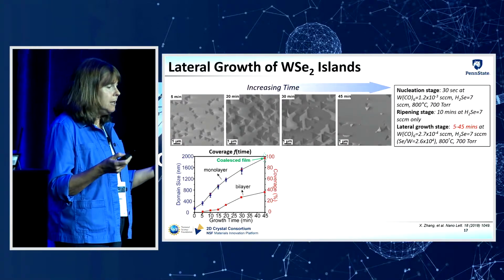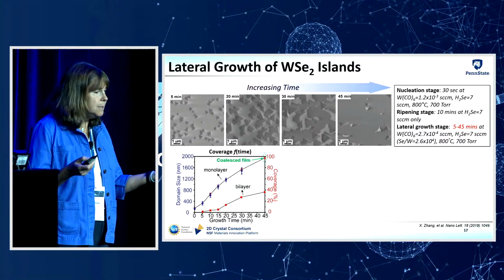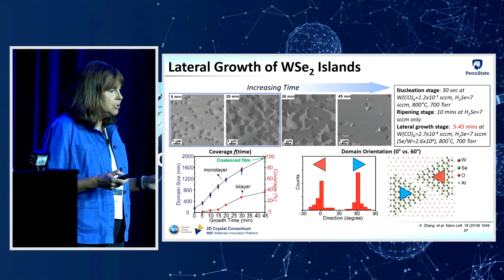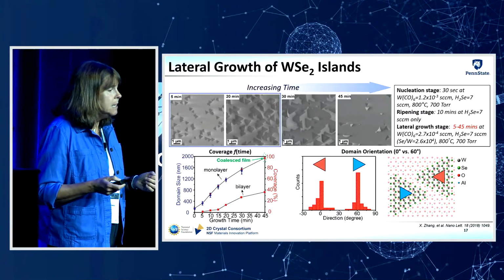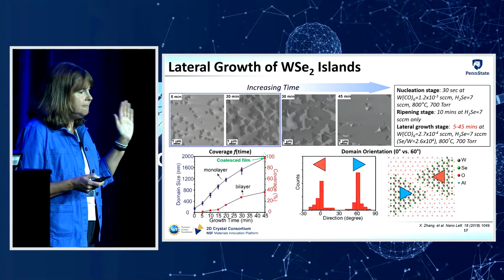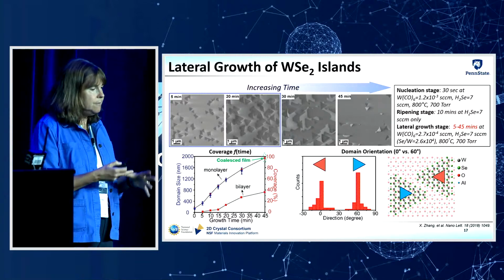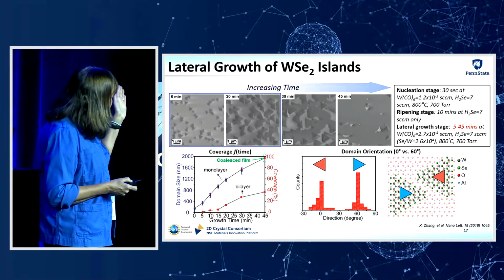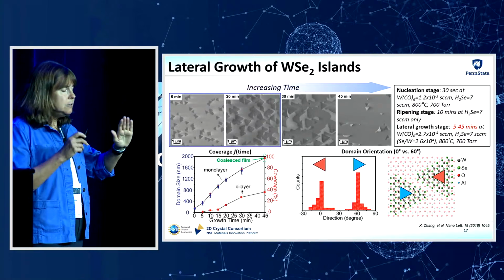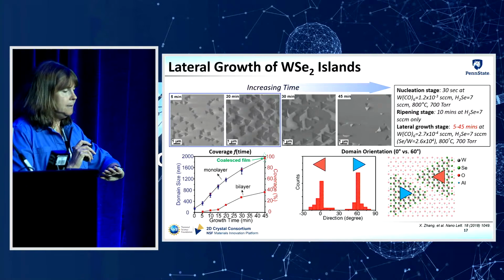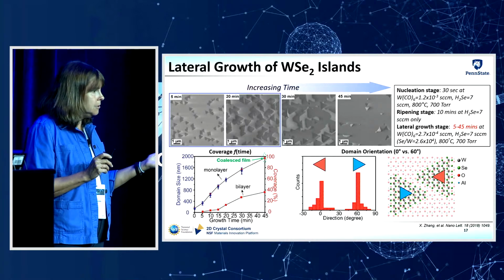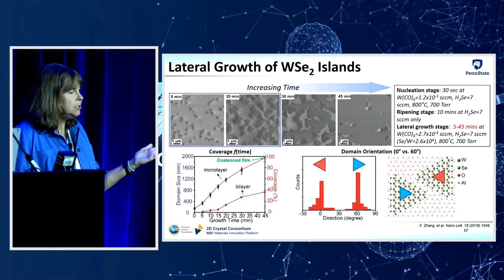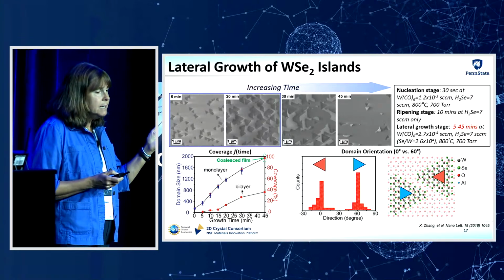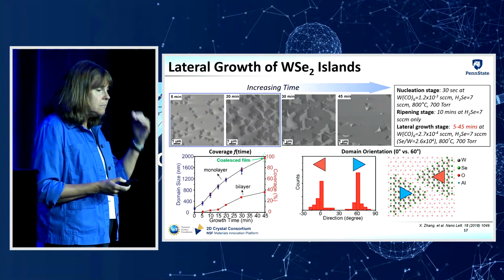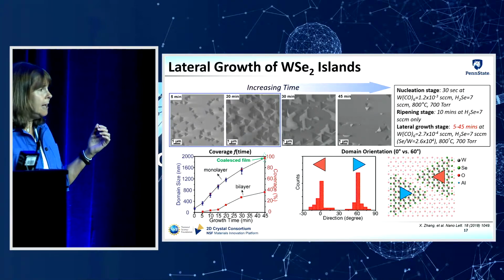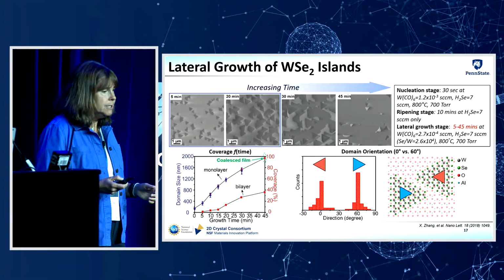So we can track how the coverage of the monolayer and the bilayer change with time. But what I want to point your attention to is the orientation of the domains. You can see that more easily for the 5-minute and the 20-minute condition before they've started to coalesce. In this case, you see these two oppositely oriented domains. These are the 0-degree and the 60-degree orientations that I mentioned earlier, and they're present at a ratio of about 50-50. So we would expect this film to have a fair number of these inversion domain boundaries.